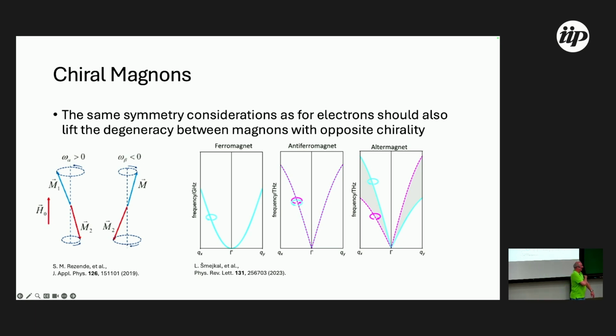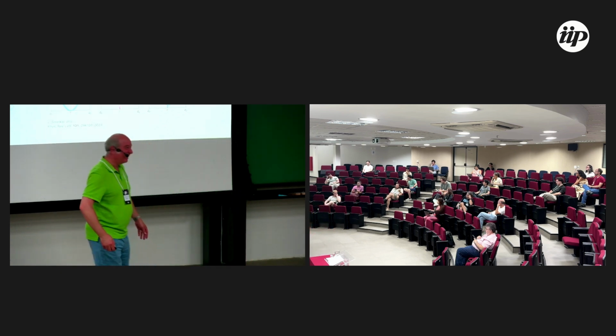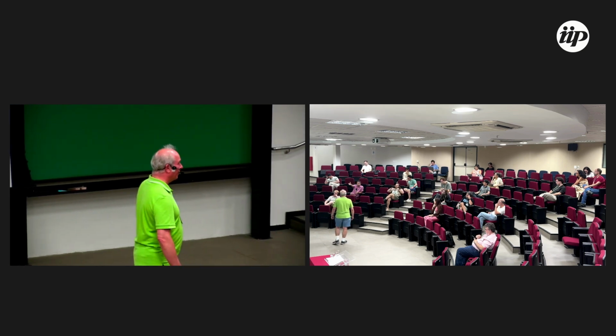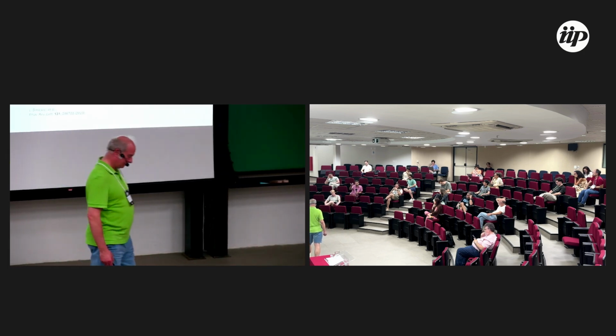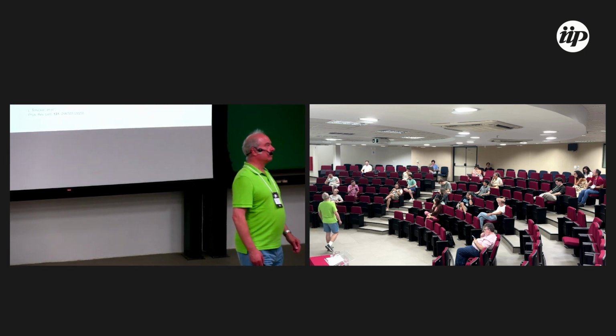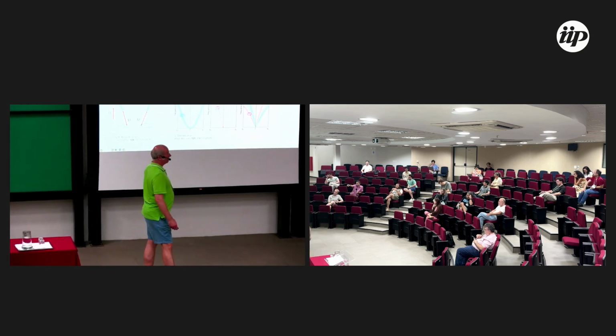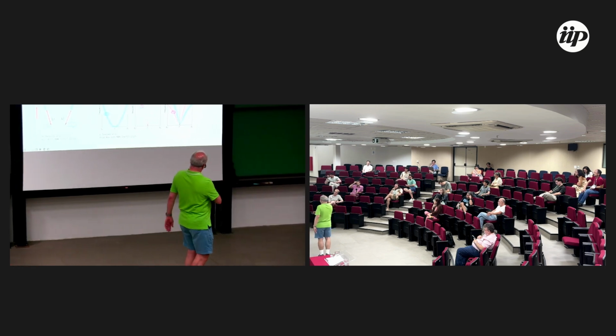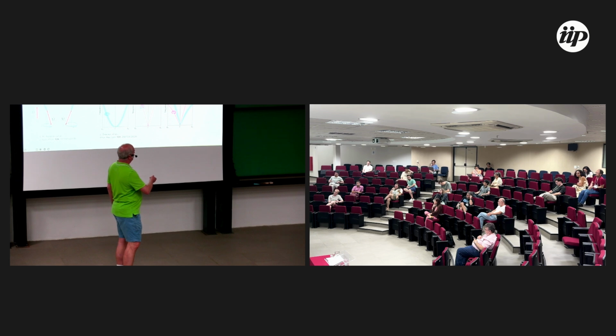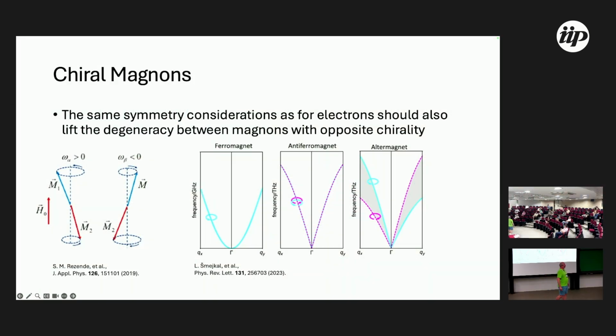I think everyone realizes why this is a hot topic, right? Every time I think about this, for instance, I think about the spin-Seebeck effect, because it is one way you can prove the chirality of those modes. For example, in the antiferromagnet spin-Seebeck effect, it exists because you create an opening between the two modes, and above the spin flop you see a change in sign. I don't know if someone is following, it could be too specific, but in the altermagnet it should be there. You're absolutely right. It could be that the spin-Seebeck effect looks very different if the heat goes in one direction or 90 degrees differently, so there could definitely be interesting situations there.